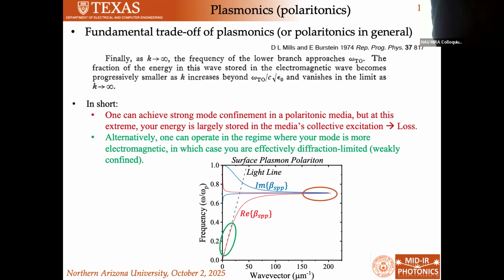So in other words, what this means is you can achieve very, very strong mode confinement in a polaritonic medium, but at this extreme, your energy is stored in the media's collective excitation. And this leads to loss. Alternatively, you can operate in the regime where your mode is more electromagnetic, in which case you'll have lower losses, but you're effectively diffraction limited. So you're weakly confined. And you can see that this is the dispersion of a surface plasmon mode. You can see that as it bends, this is the light line, so this would be light propagating in the material. As your mode bends away from the light line, as K gets much larger, your loss, the blue line, goes through the roof. So it's this trade-off. There's always these trade-offs.